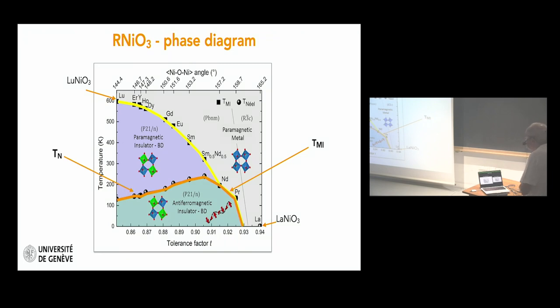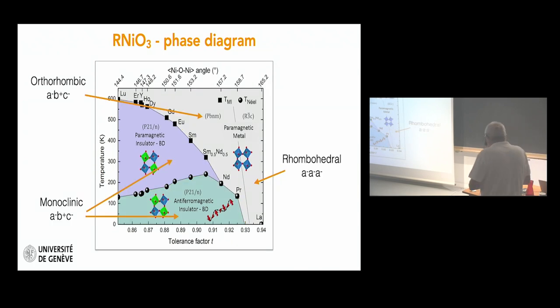This is a magnetic transition that is now going this way, and you see that neodymium nickelate and praseodymium nickelate have a joint transition, so you have a metal insulator transition accompanied by the magnetic transition. For the others, it's decoupled. The structure, lanthanum nickelate is a special member of the family. The structure is rhombohedral, A minus, A minus, A minus. The others are orthorhombic in the metallic phase and turn monoclinic in the insulating phase.